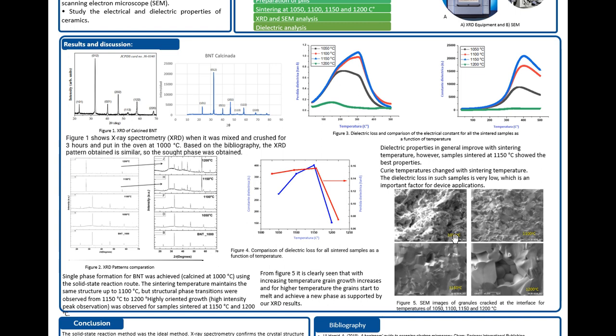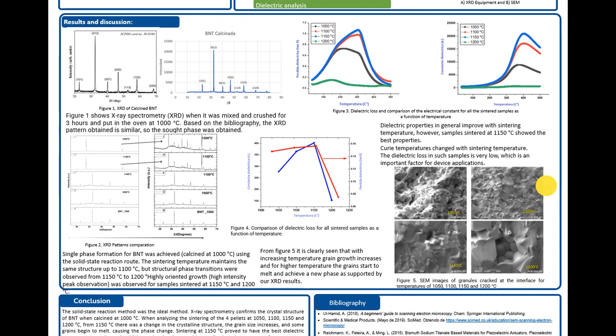We get those images from the SEM, and comparing with the XRD patterns, we can see that at the temperatures of 1150 and 1200, there's a change in their microstructure. We can see it a little bit from the SEM, and from the XRD patterns we can see how the change is very clear from the other ones. And here we can see at this temperature of 1150 is when the change occurs; they are starting to melt and change their grain size.